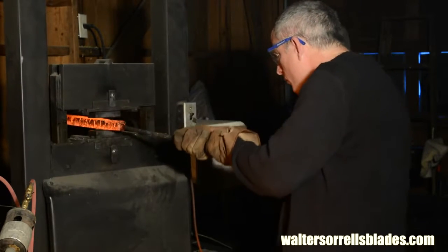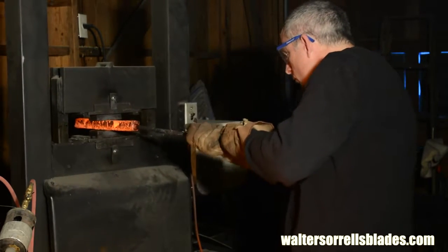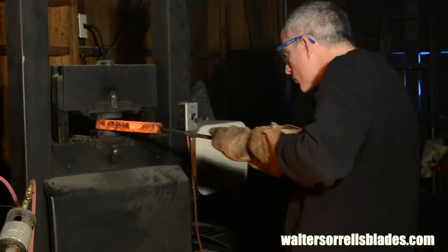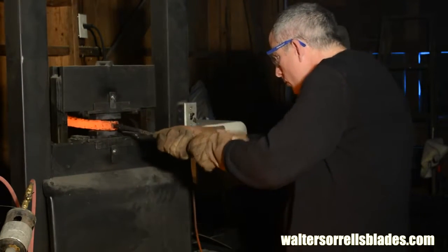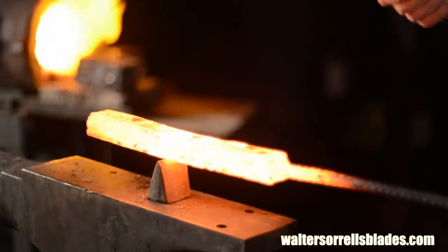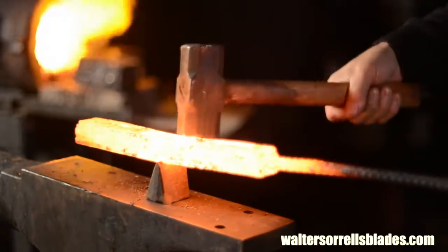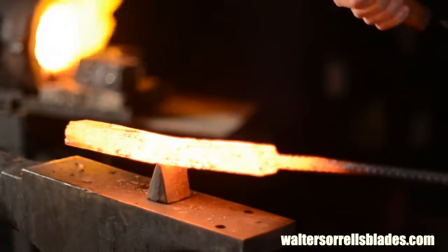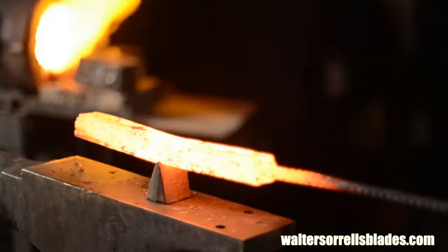So, two ways of building up layer count. Way number one, the old school method, is to use a hot cutter of some sort to cut the billet in half and then fold and re-weld. You can do it with a hot cutter on the press, or you can use a hardy tool like this.